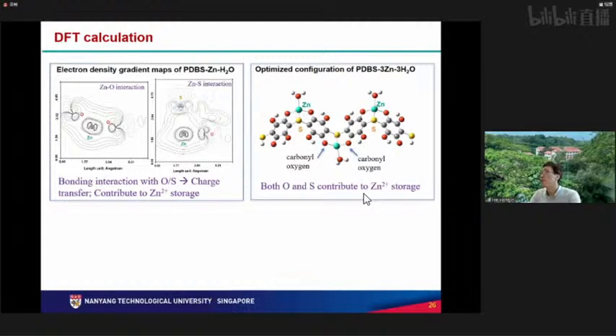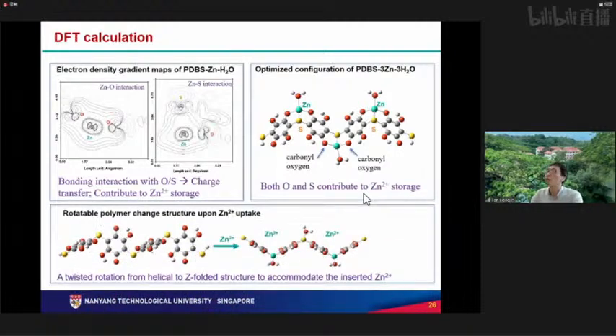And for example, this is two units of the polymer chains. So we have the zinc on one of the benzene rings, another on the other benzene ring, and somewhere in between. Okay, this is in between. So we have, say, 3 zinc ions integrated into this one unit. Okay. And also because the polymer chain is rotatable during the process, that means if zinc ions go in and out, it may cause rotation to have a better accommodation of zinc ions. So this is of course based on thermodynamic molecular dynamic simulations to find the most stable structures after uptake of zinc ions.